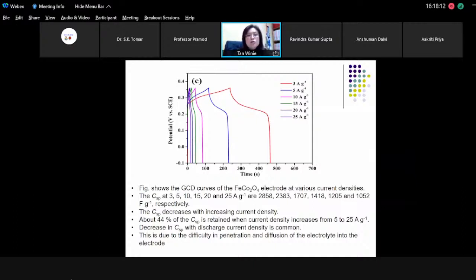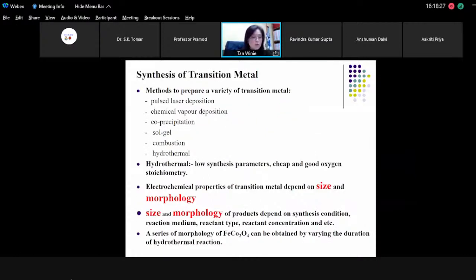So this decrease in the specific capacitance with the discharge current density is actually common, because this is due to the difficulty in the penetration and the diffusion of the electrolyte into the electrode. So this is what I want to show you on the synthesis of transition metal compounds. You can use various methods as listed here, but we choose to use hydrothermal.